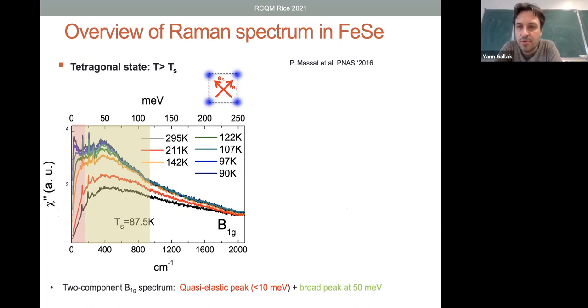But you see there is some structure at higher energy that is much less critical, and we believe it's associated more to local spin physics. So there seems to be this two-component response, which is relatively unique to iron selenide. This is not something that we see in barium 122.